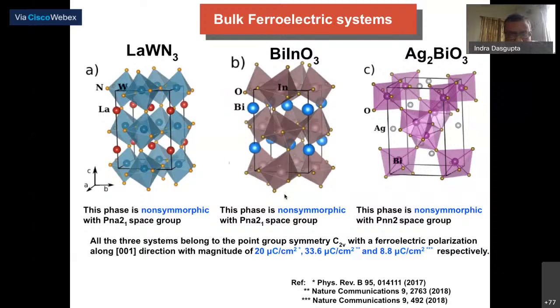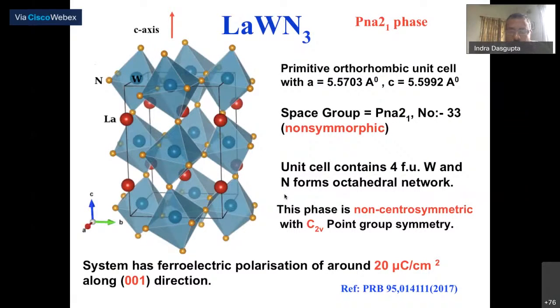So you can see they have the same point group symmetry, which is C2v, but their non-symmorphic symmetry operations are slightly different, while these are identical for LaWN3 and BiInO3, but different for Ag2BiO3. To begin with, I'm going to take this LaWN3 in its orthorhombic perovskite structure and show you that it indeed shows the Rashba effect. So how do we do that? This is LaWN3. As I told you, it shows a ferroelectric polarization along the 001 direction, which implies that the system has an intrinsic electric field along the 001 direction, which also implies that this is an ideal candidate to host the Rashba effect.